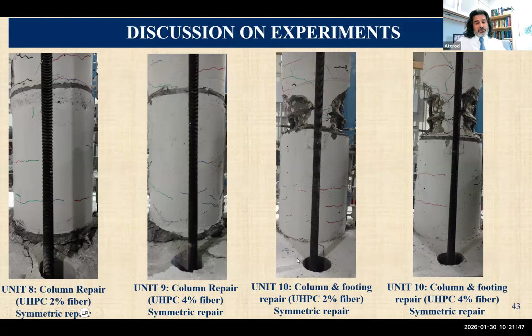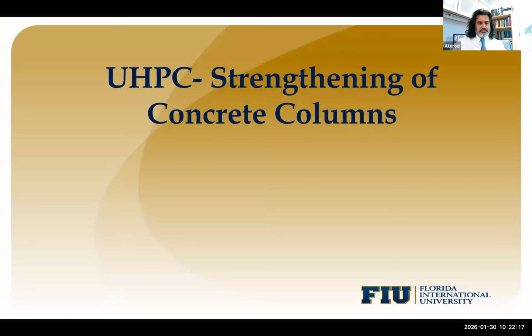That means that if you retrofit a column, you also have to retrofit a little bit around the column in the base, because if you don't, you see the left-hand side? In fact, we learned it the hard way. In the left two columns, we didn't retrofit the base, and the failure was in the base because that's where the maximum moment is. Then in the next two, we also repaired the foundation, and now we shift the damage to above.